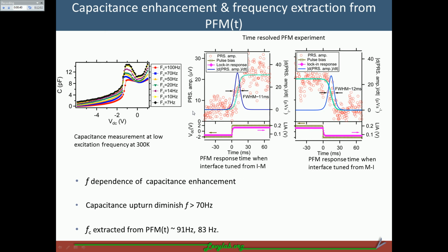We measured the response time of the piezo response signal and find that it was around 11 milliseconds and 12 milliseconds, which corresponds to frequencies around 91 Hz and 83 Hz. Such frequencies match well with the frequency dependence of the capacitance signal.